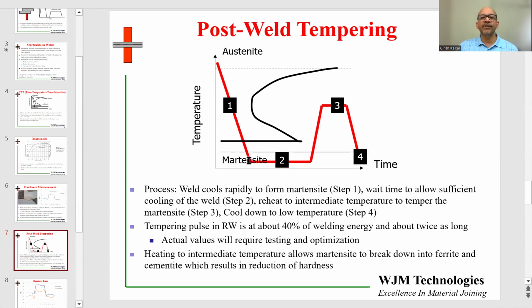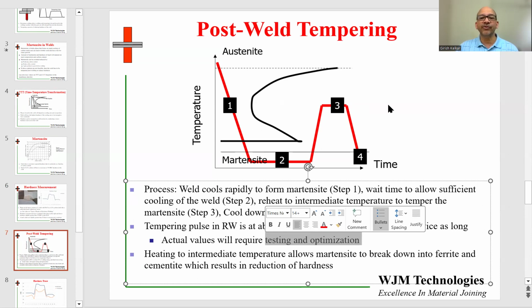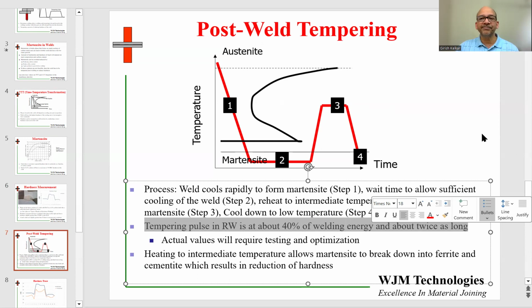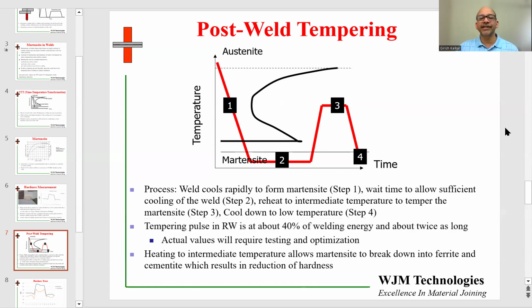Now, once the martensite is formed, we wait for some time to allow the whole process to go through. And then in step 3, we increase the current. We again send a second pulse, which is the tempering pulse, to a level where we heat up the martensite, but not so high that we again transform it back to austenite. Now, how would you know that? Now, that is difficult to measure inside a weld, so you do have to conduct some testing and optimization to find out exactly how much current you would use. But typically, I would recommend starting with about 40% of the welding energy and about twice as long as the welding pulse. So that's a starting point for you to do some experimentation.